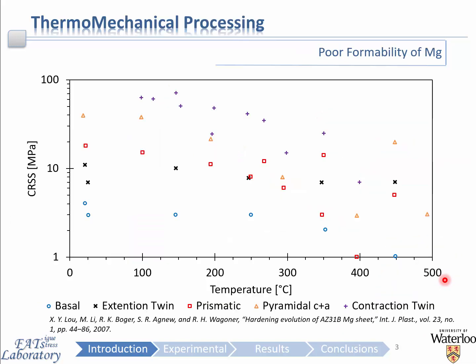So one might ask themselves, if the properties of forged magnesium are arguably superior, why hasn't this material been utilized for such components already? The answer to this question has many facets, one of which is the poor formability of magnesium at room temperature. This figure shows the critical resolve shear stress versus temperature for a variety of different deformation modes. At room temperature, basal slip is the first one that becomes active in the lowest critical resolve shear stress range of 2 to 4 megapascal.